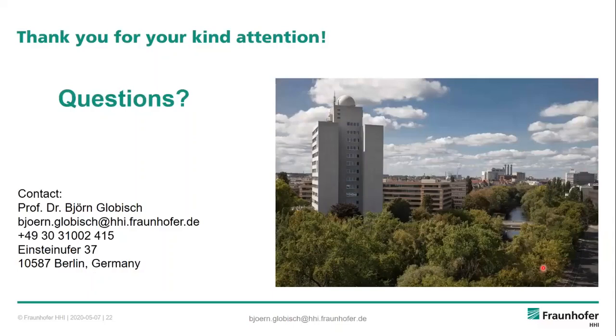Elena Martinez asked how different can the coatings be to be able to be distinguished as different layers. Is it possible to know the composition as well? Yeah, so this measurement scheme mainly measures the difference in refractive index of the coating. So if you have really similar coatings, it's getting harder and harder to distinguish them. So what we need is a difference of approximately 0.1, 0.05 in the refractive index in order to distinguish the coating. Okay, and is it possible to know the composition? Yeah, you should know the composition beforehand. It's extremely important. So if you want to measure really thin layers, you have to know the composition beforehand.